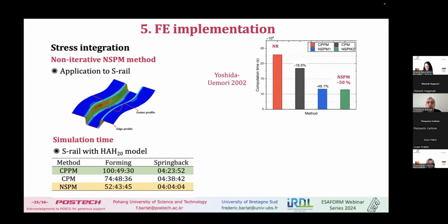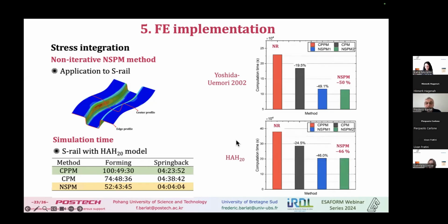And it was done with a Yoshida-Uemori model, and we got about a 50% reduction in the time. We did this with HAH20, and we get about the same time reduction as well. So you just need to compare the red and the blue, because this is the only one I am talking about here.